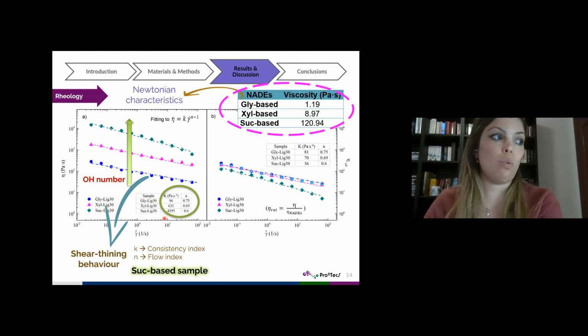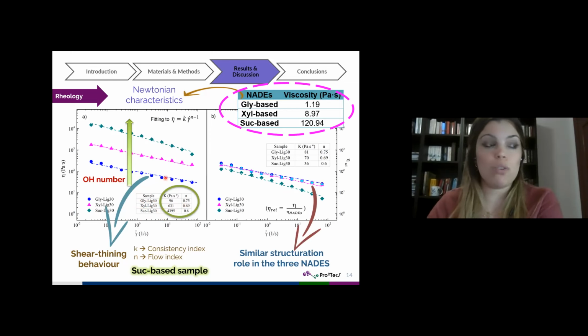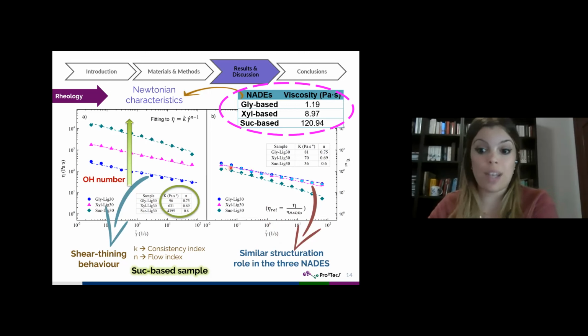On the other hand, just in order to elucidate the effect of NADES viscosity on the viscous flow properties of the thickened formulation, I plot here the relative viscosity versus shear rate, obtaining similar viscous curves for the three kinds of NADES used. This indicates that lignin exerts a very similar structuration role in the three NADES, and the differences in viscosity are mainly due to the NADES viscosity. So we achieve the same structuration degree in all samples when dispersing lignin.